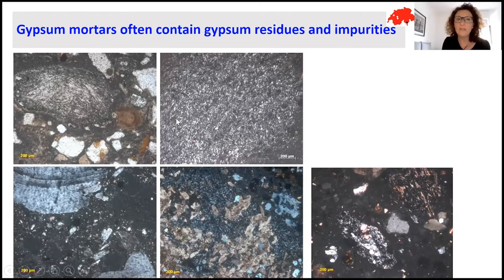Similarly to the lime mortars, the traditional gypsum mortars also contain gypsum residues and impurities, and I can have information about the raw material used for the gypsum production. For example, in this case, I see, which is very common, within a residue of gypsum stone, some residues of calcite crystals, because they are an impurity in the gypsum stone, and they do not react at the lower temperature needed for the binder production